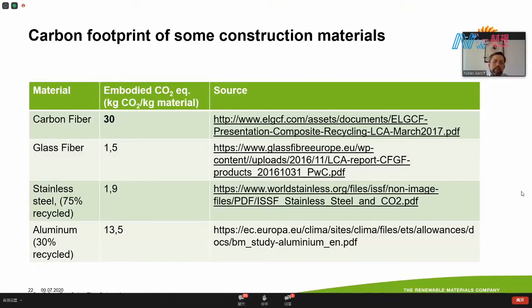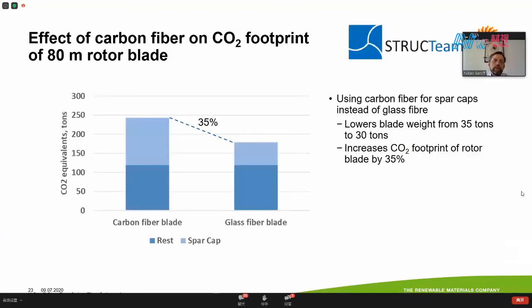And how does this high carbon footprint impact the rotor blade? Well, we did a study in the STRUCTeam, and here we compared 2 different rotor blades, one that is using glass fiber for the spar caps and one that is using carbon fiber in the spar caps. And what we observed was that if you use carbon fiber in the spar caps, the blade weight decreases from 35 to 30 tons, which is good. But the carbon footprint increased by 35% from about 170 tons to close to 250 tons of carbon dioxide equivalents for an 80-meter rotor blade. So that's a problem, and that's only one example showing that even small amounts of carbon fiber may have a significant negative effect on the carbon footprint of your product.